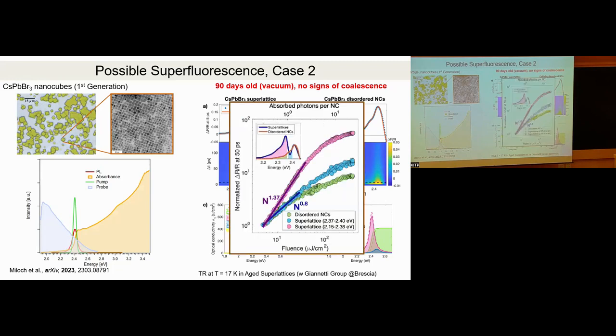And when we studied the strength of this resonance versus the excitation fluence, we saw that for some range there is a superlinear power dependence with an exponent around 1.4. In the 2018 study, it was 1.5. So we think in this case we might see a similar effect.